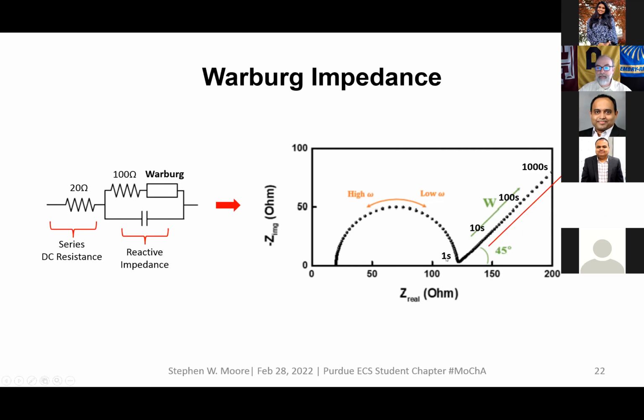And the longer I continue to apply lithium ions, and this lip right here, the RC time constant of this is usually the semicircle ends after about 1 second, which means this capacitor right here charges in about 1 second. For 18650 lithium ion batteries, this is a reasonably good rule of thumb that this capacitor fills in about 1 second, and then the Warburg impedance takes over after 1 second. So if I apply a 1 second pulse, I'll generally see this reactive impedance, but then I start applying 10 seconds of pulse or 100 seconds of current or 1,000 seconds of current. The impedance of my battery continues to grow over time as those lithium ions are having to engage in the diffusion process in the electrode. And so this is the reason why your battery voltage sags as you're using your battery.